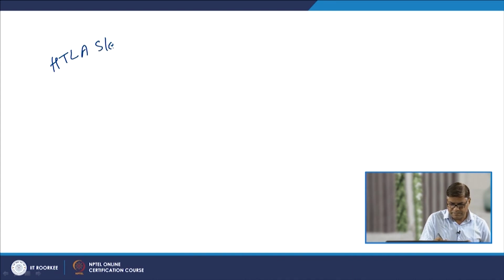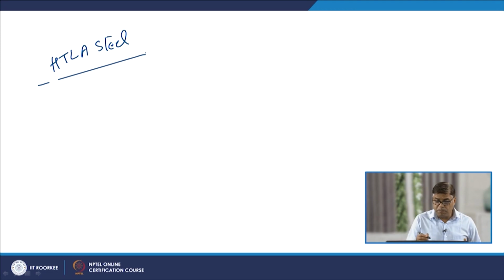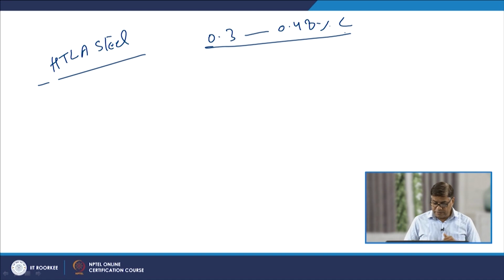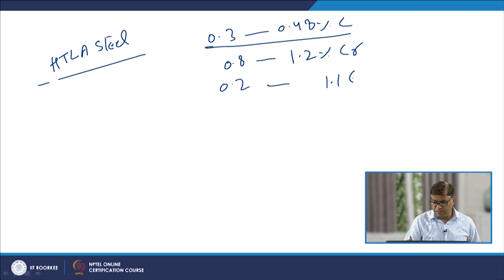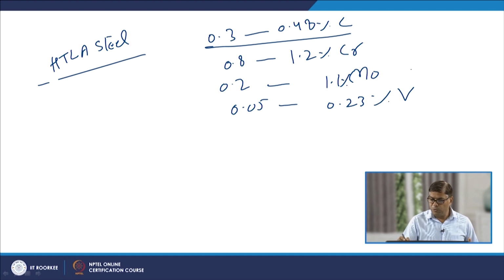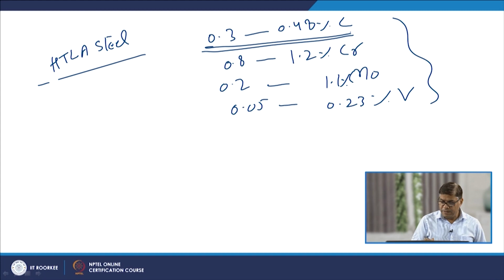Since the heat treatable low alloy steels have quite a good percentage of carbon, like 0.3 to 0.48%, while there is a little amount of other alloying elements like 0.8 to 1.2% of chromium, 0.2 to 1.1% of molybdenum, and in some of the compositions a little amount of vanadium as well, like 0.05 to 0.23% of vanadium.